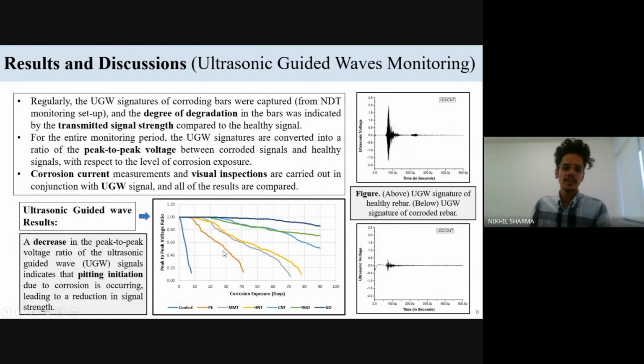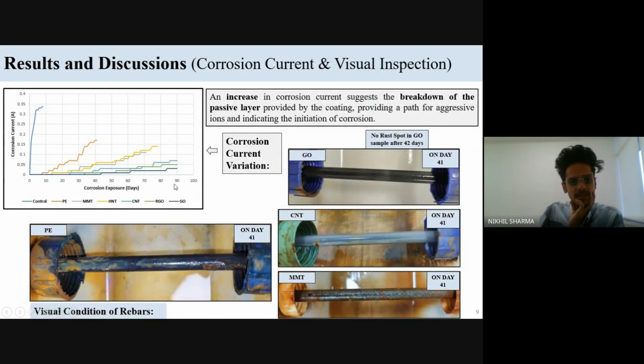And this is the variation in all the samples, and we can see the ultrasonic signature of graphene oxide after 90 days. For example, for plain epoxy, we closed the corrosion testing because after 41 days, their ultrasonic signatures were completely depleted. Therefore, the sample is removed from the corrosion. Other samples either continue for the 90 days or are removed once their signature is completely depleted. In corrosion current, for the same monitoring period, the corrosion current is the least for the GO modified epoxy coatings, and for the plain epoxy coatings, it reaches up to 0.2 ampere in 41 days.